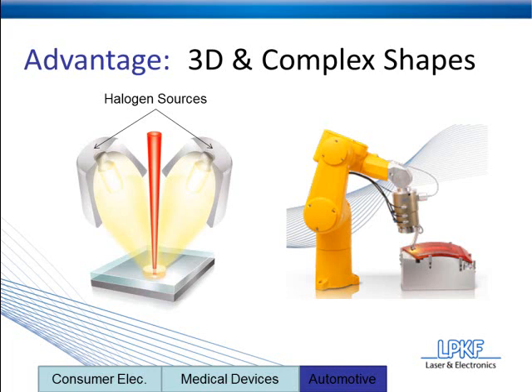The second advantage is that the halogen lamps are essentially preheating the plastic around the laser. So the laser won't have to work as hard, or it won't take as long for the laser to melt the plastic and create a weld seam, and can reduce cycle times by up to half.